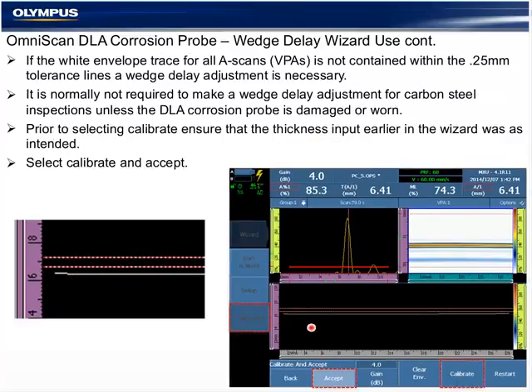If the wedge is actually worn, or if there's a slight velocity difference for your carbon steel making the thickness reading out of tolerance, the calibrate function is available, and this is done on one step or one thickness in the middle of the inspection range. This will bring the wedge delay into tolerance, but in this case it exists on a normal carbon steel calibration block with a wedge and probe showing no visible damage.